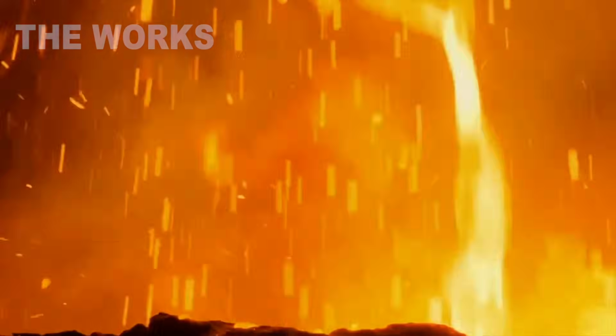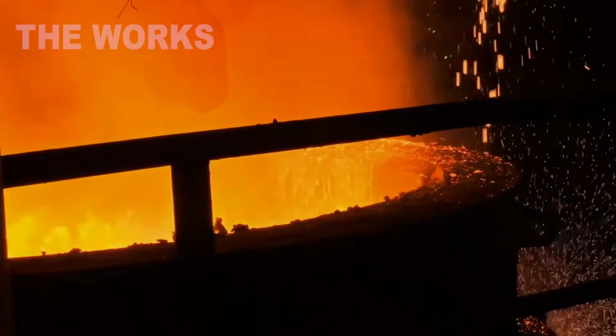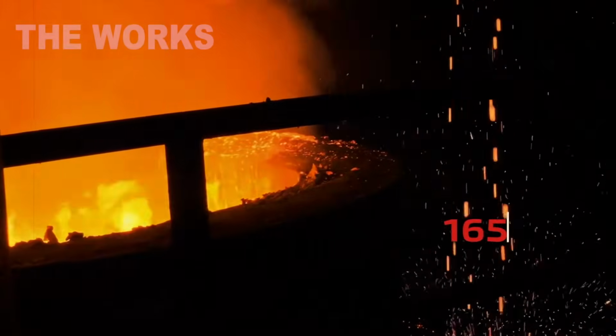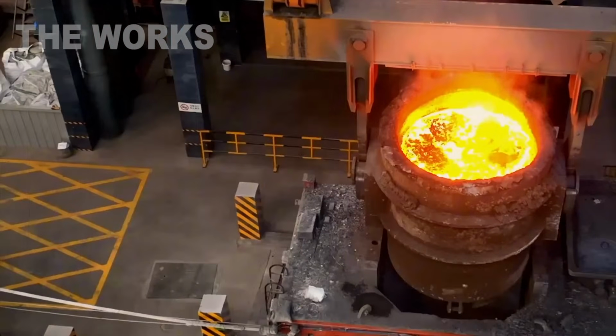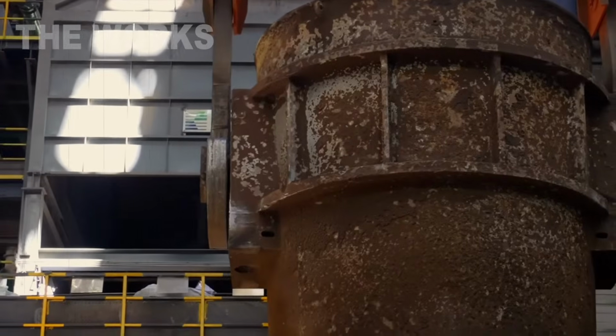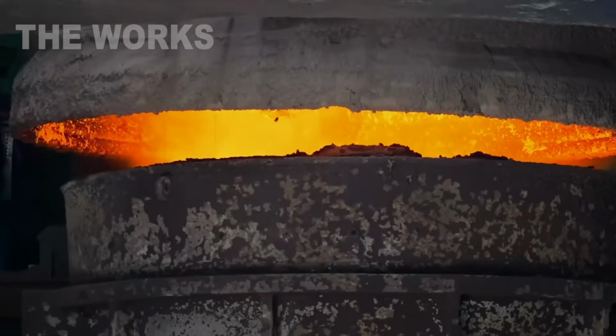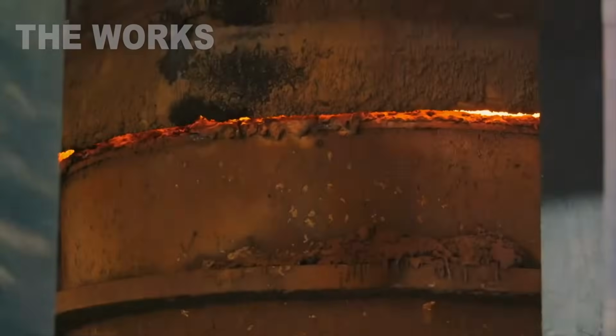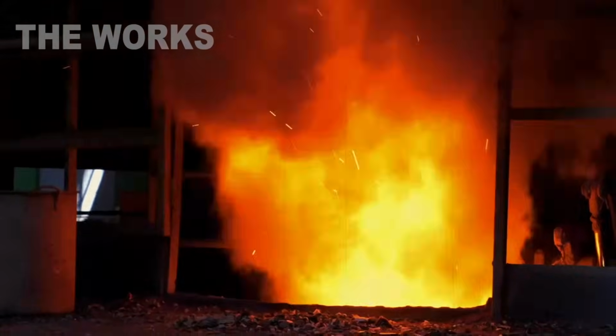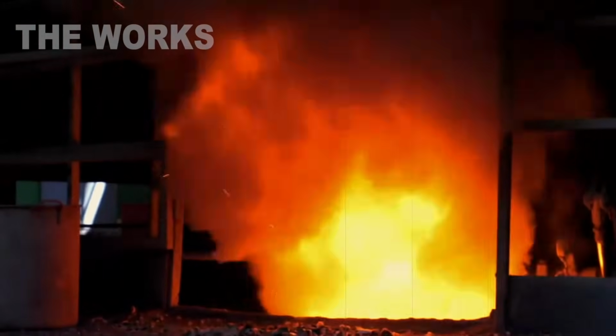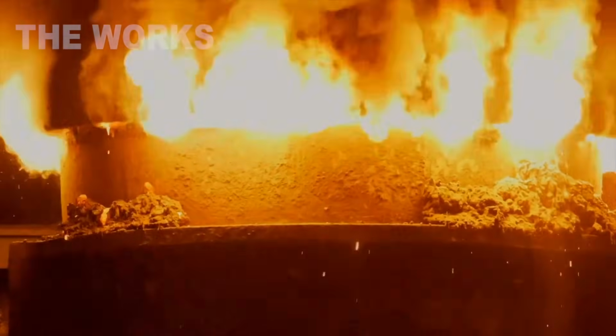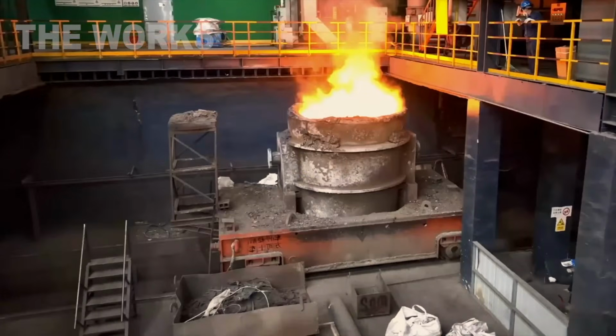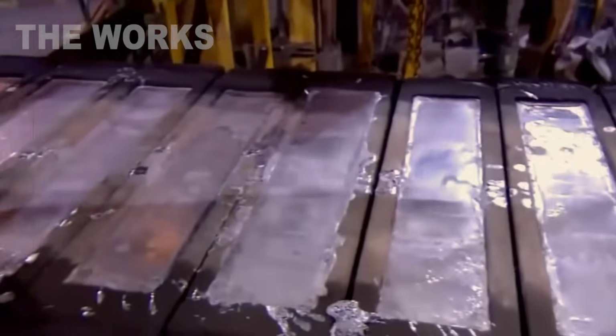A stream of white-hot metal and slag bursts out, flowing down a channel into an enormous ladle. The stream's temperature is around 3,000 degrees Fahrenheit. The metal glows bright orange, almost white. The heat radiating from it is so intense that workers stand dozens of yards away, protected by special screens and fireproof clothing. Slag floats to the top and is drained off separately. The ferrochrome cools in massive molds, transforming into solid ingots weighing hundreds of pounds. These ingots are later crushed into pieces of the right size for sale to steel mills.